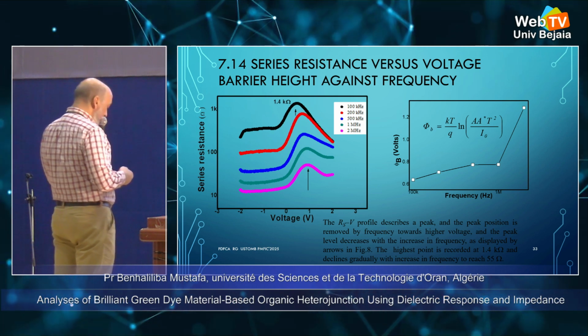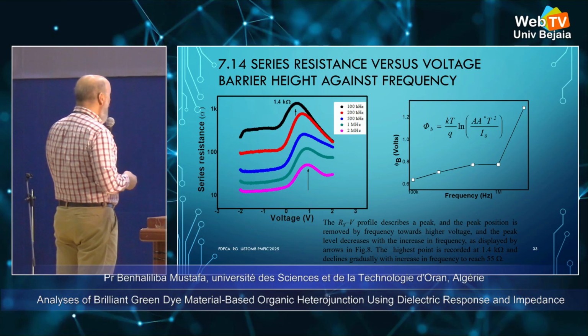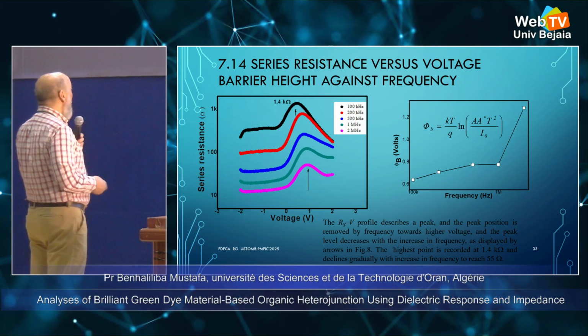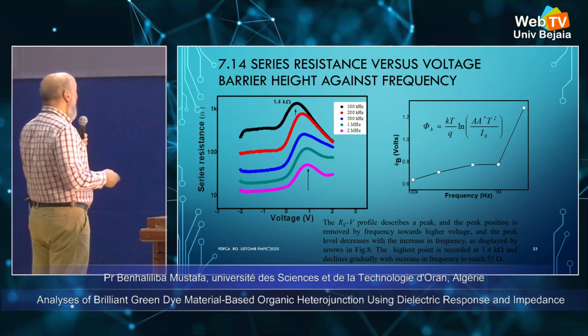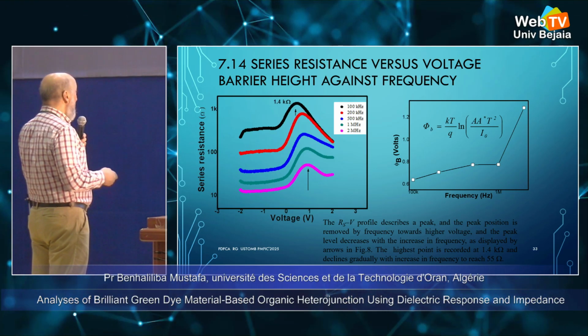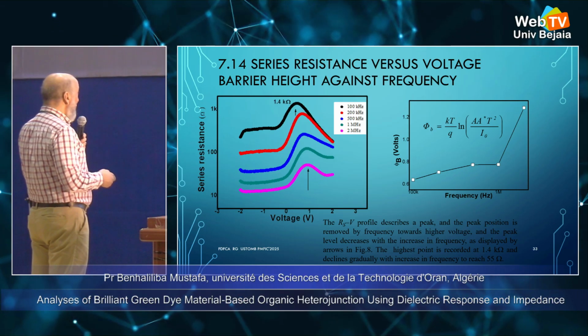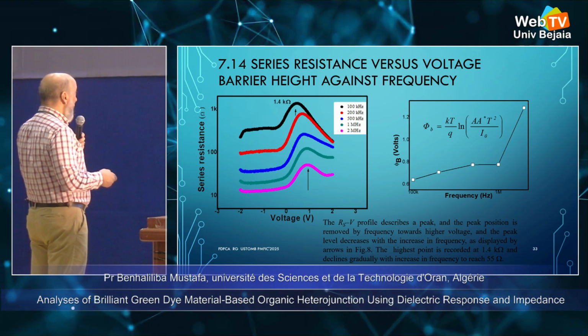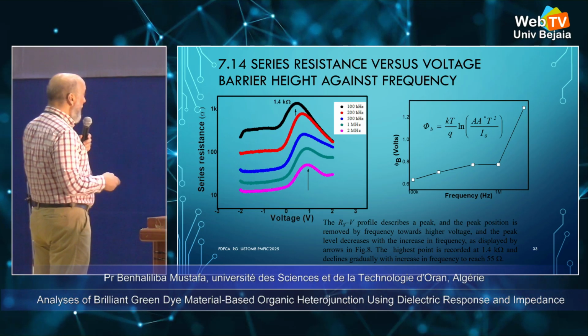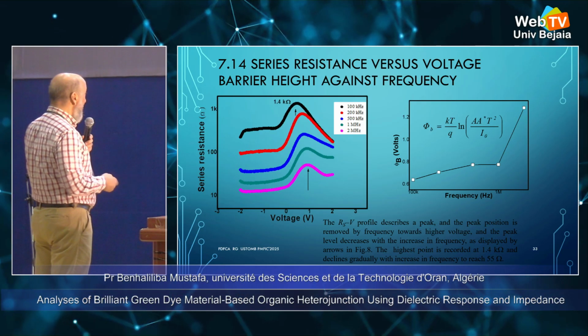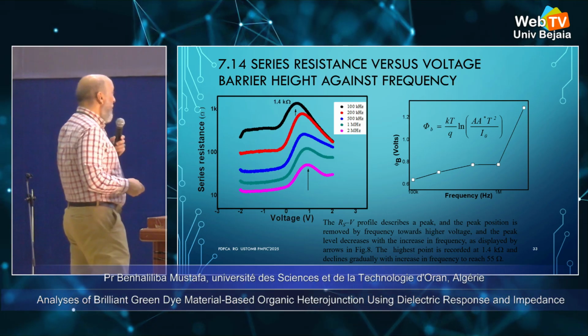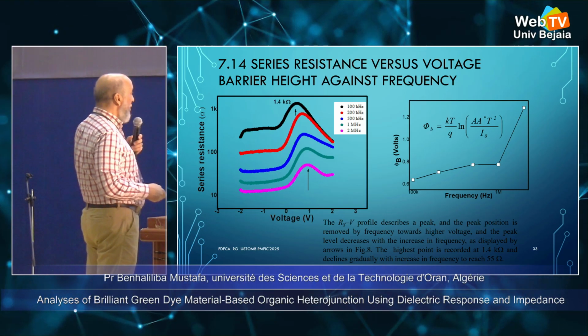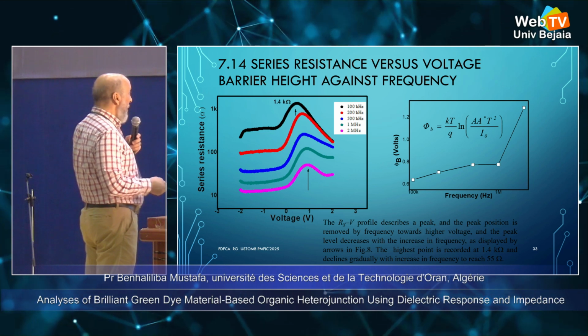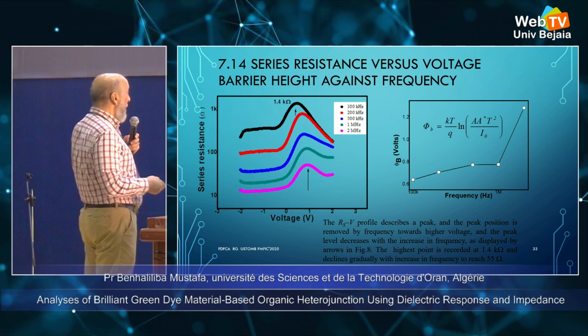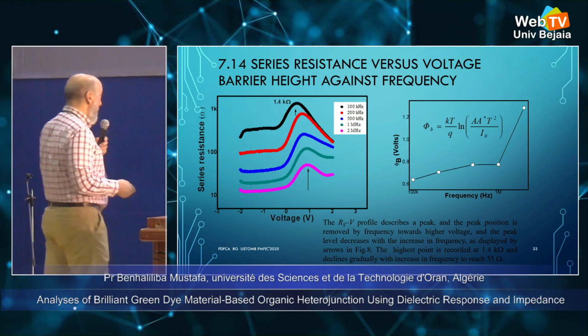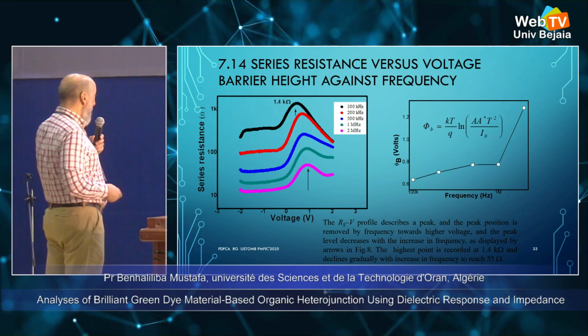Here we plot the series resistance experimentally versus voltage. We have this curve which displays a peak, and the peak is at different frequencies from low frequencies to high frequencies. And here we have plotted the barrier height versus the frequency using this formula, Phi_b versus the temperature and saturation current. We have an increase.